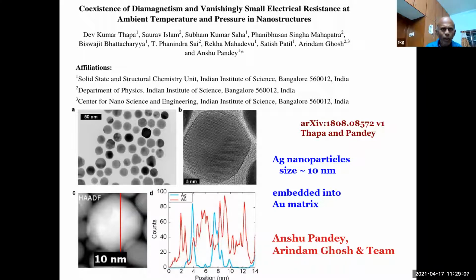And they found remarkable diamagnetism phenomena, which is fluctuating. You see it once in 10 samples or once in 20 samples. And then electrical resistance falls below the lowest known at those temperatures, much lower than copper or gold at room temperature. So it is a nanocrystal embedded in a gold matrix. The dimensions of the nanocrystals are of the order of 10 nanometers.